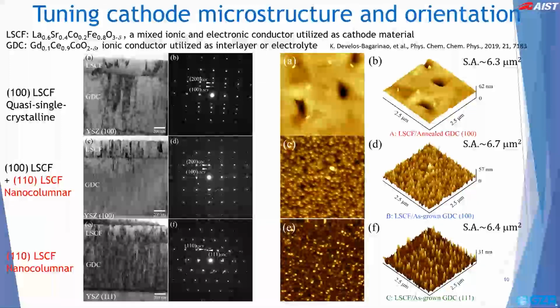This slide shows some of the results we have obtained in our investigation of various cathode structures. Here, we used a single crystal substrate, yttrium stabilized zirconia or YSZ, with orientation of 100 and 111. On top of the YSZ, using the pulsed laser deposition or PLD method, we also prepared a gadolinium-doped ceria, or GDC, which is normally used as an interlayer when using YSZ as electrolyte. This is to prevent the chemical reaction between the cathode, in this case LSCF, and the YSZ electrolyte. We also varied the GDC microstructure by high temperature annealing.